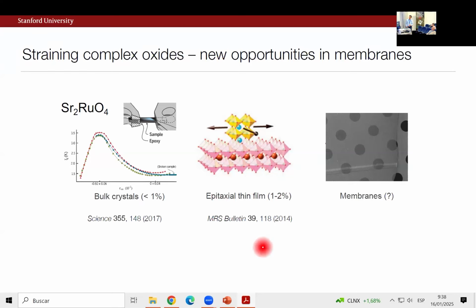In the case of epitaxial films, of course, the details of the system and the growth matter, but on the scale of 1 to 2%, certainly by 2% for reasonable thickness films, you start to see dislocations, defects, and so forth, right? So there are some bounds to this. And in terms of the membranes, I guess the question is to what degree can we use this very interesting materials geometry to make measurements and new directions in this regard.